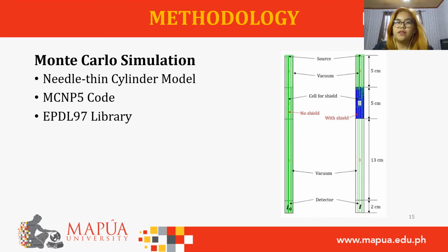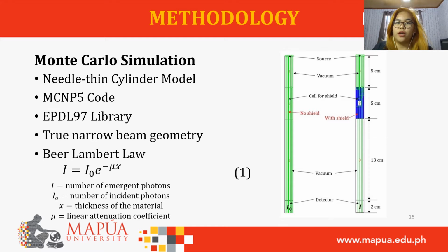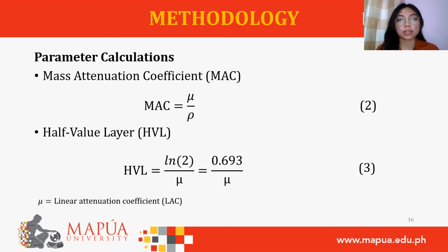Considering that the model demonstrates a true narrow beam geometry, the number of incident and emergent photons can be related by the Beer-Lambert law, where the mu, or the linear attenuation coefficient, can be calculated. The mu is related to the mass attenuation coefficient, which is to be discussed in the following slides. The mass attenuation coefficient can be calculated by dividing the linear attenuation coefficient by the density of the material. The half-value layer can be calculated by dividing the natural logarithm of 2 by the linear attenuation coefficient.